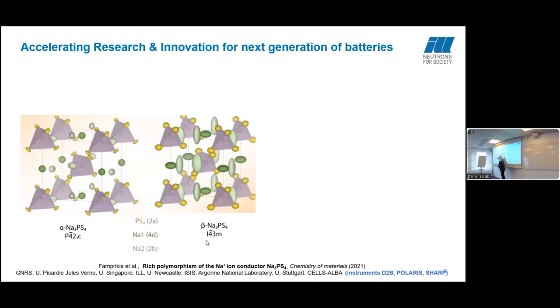Green are the sodium ions. There are two different positions, represented by different shades of green; yellow is sulfur and blue is phosphorus. So you have these thiophosphate tetrahedrons and then sodium ions in between. And when we go from the tetragonal alpha phase to the cubic beta phase, the sodium ions change positions along the c-axis and the tetrahedra reorient a little bit. So the symmetry becomes simpler, we get a cubic phase. That seems pretty straightforward.